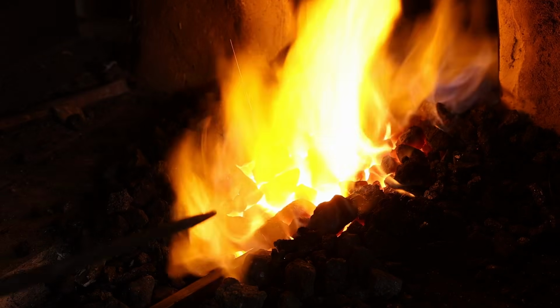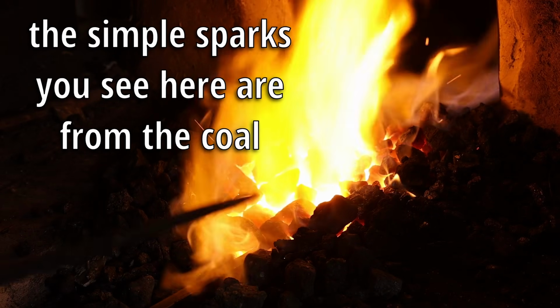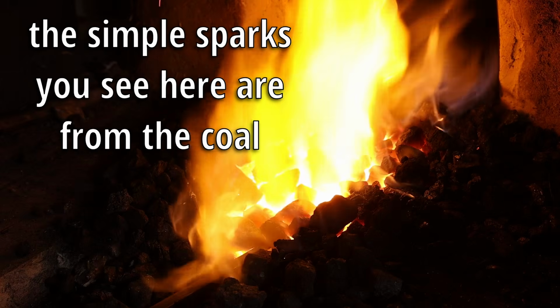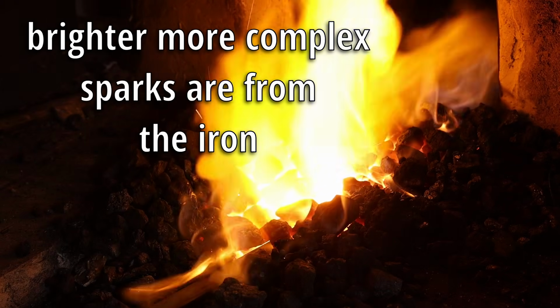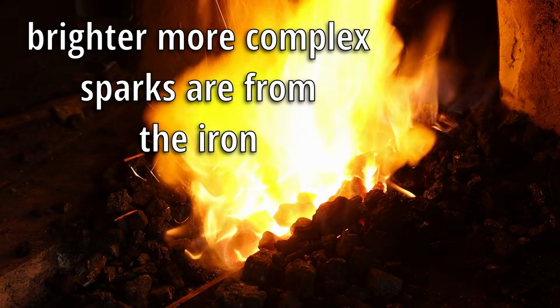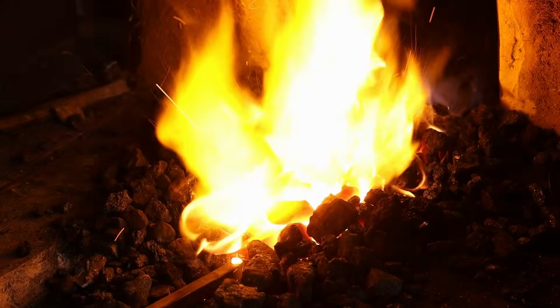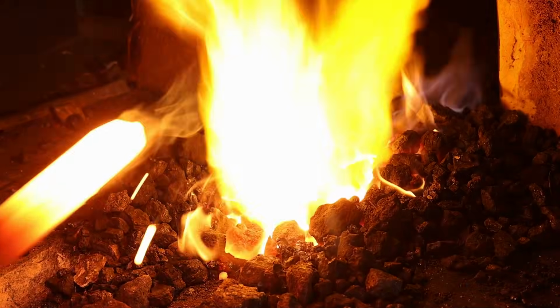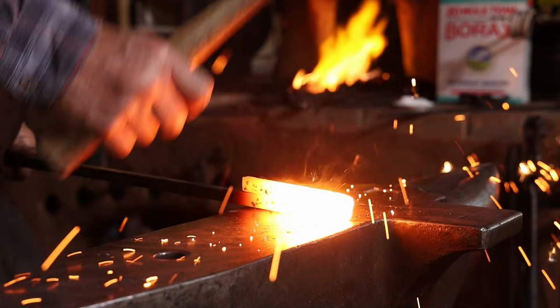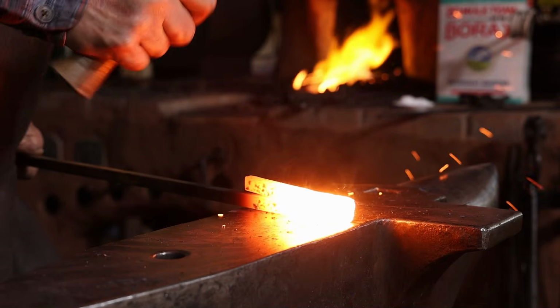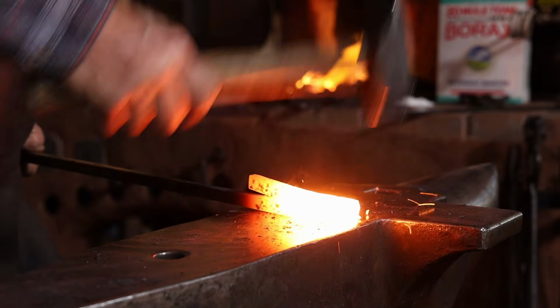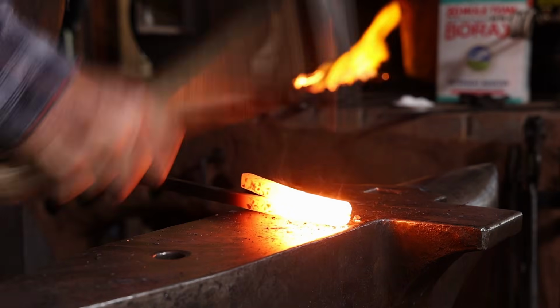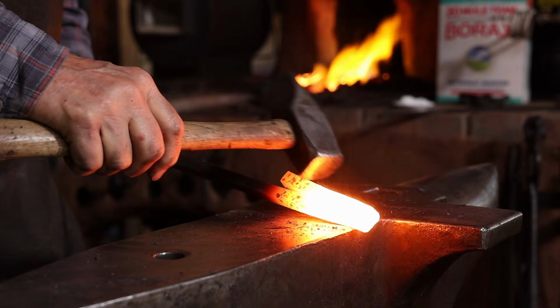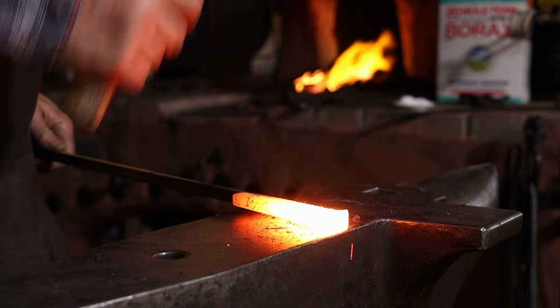You don't want a lot of sparks. Sparks from the iron and the welding flux is okay, but since the borax doesn't have any, sparks would be bad. That means you're burning the material. That's a welding heat. You're going to go with light, rapid blows starting at the end and work back, and only the part that's hot. This section up in here is not hot enough to weld. There's no reason to hammer that.